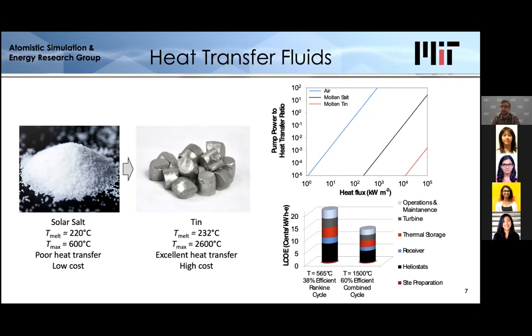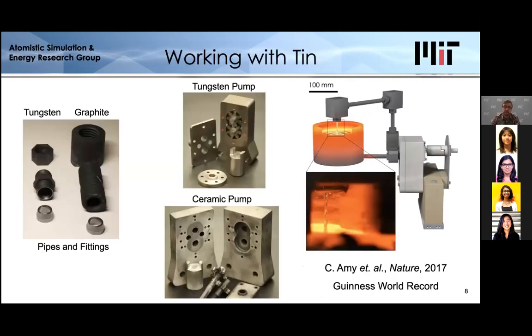But we obtained a lot of really good information and learned a lot of great stuff about how to work with tin and its opportunities as a heat transfer fluid in other contexts. So we designed and fabricated our own pipes and fittings for tin made of graphite and tungsten. Figured out how to make pumps that can pump molten tin at very high temperatures. And we actually demonstrated pumping liquid tin at 1400 degrees Celsius in 2017. We published a Nature article about that, and also have the Guinness World Record for highest temperature liquid ever pumped.